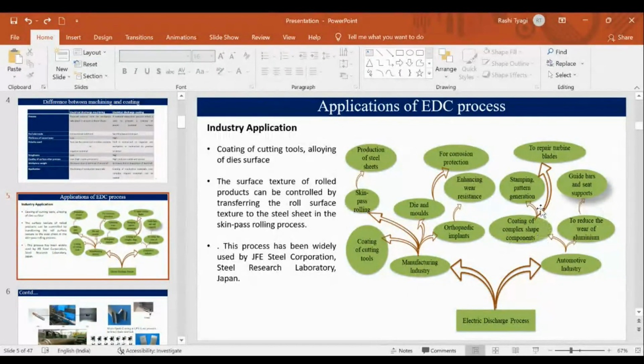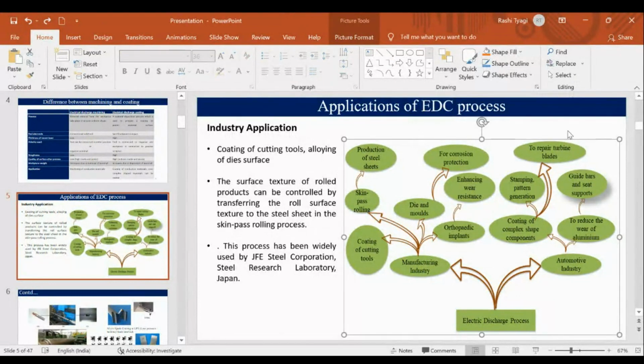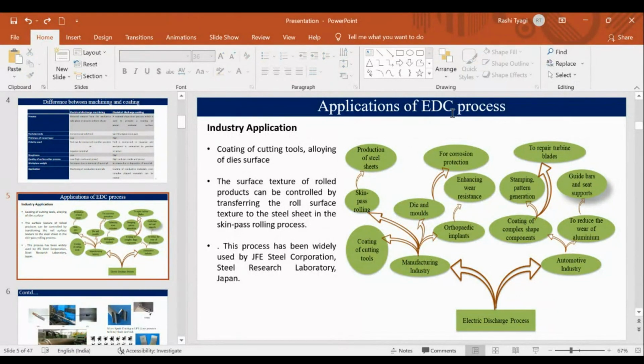Other applications include coating of complex shape components, as I have already told you. Then to reduce the wear of aluminum. Basically, aluminum is a lightweight alloy that is widely used in guide bars and seat supports, so we can do coating of the aluminum. Also to repair the turbine blade. Basically, the turbine interlock surface is subjected to vibration, and there we can use the EDC process to deposit the coating, because EDC can be used for repairing. Multi-spark coating has already been used to repair the turbine blade, because in EDC it is possible to deposit a thick coating.